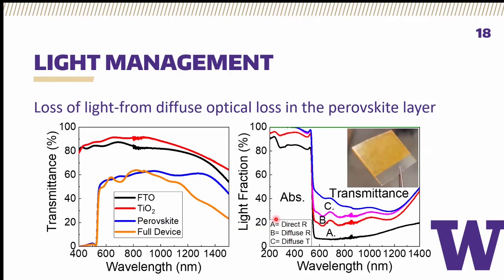So to figure out exactly what was going on, we took our perovskite devices and did transmission measurements on each individual layer, and saw a significant amount of transmission in the region of interest, 850 to the bandgap of the perovskite, 850 is the bandgap of the CdTe. And we saw most of the light losses we were observing are in the perovskite layer itself.